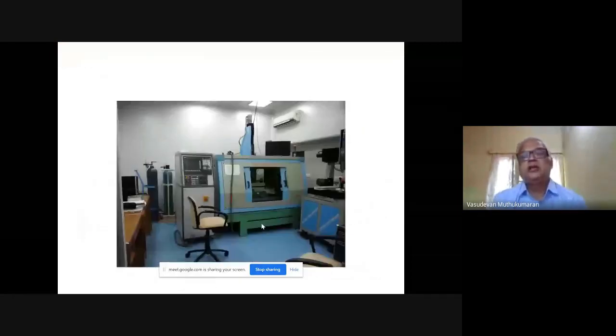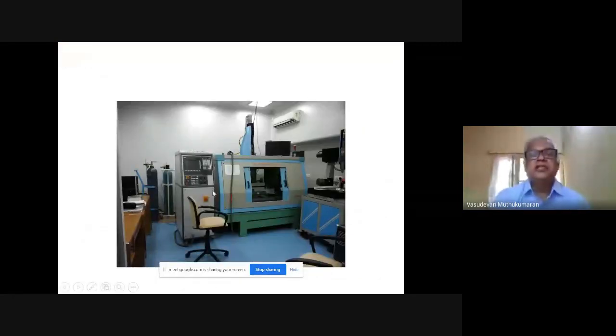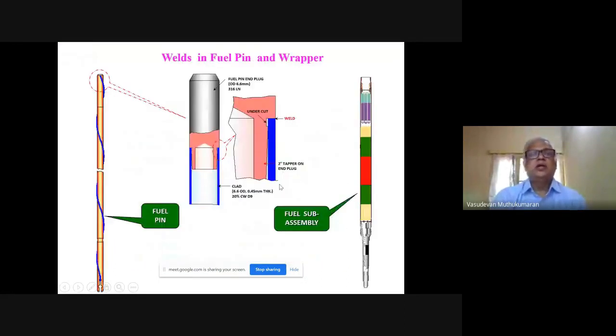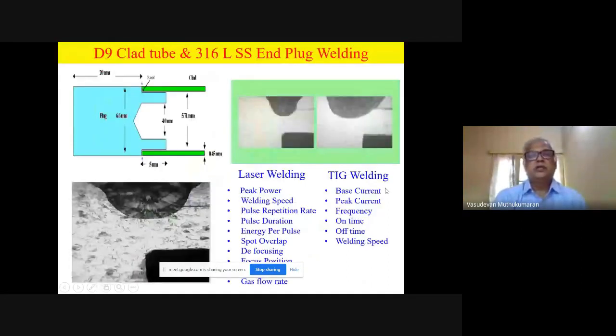This is a CNC controlled laser welding system. You can see the controller, and this is the laser welding system. It's an enclosed one. You can see this is a fuel pin, the typical fuel pin. These are the end plugs at the top, and this is the center portion. Of course, the fuel sub-assembly we have already seen. In this cross section diagram, this is the end plug material and this is the clad tube. Here we need to do the welding. We developed it successfully. You can see the cross section after welding, and we could achieve full penetration, defect-free.